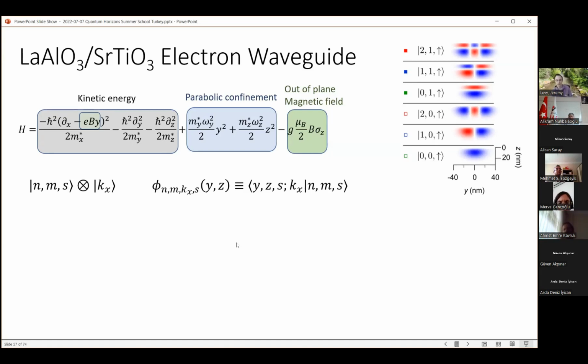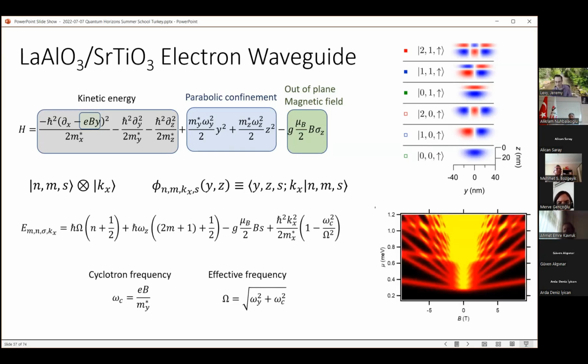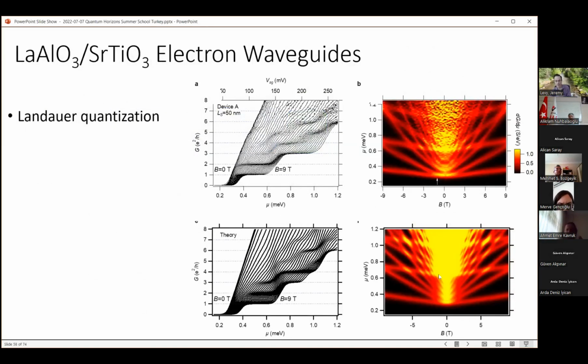And the energies themselves will shift in a magnetic field. And this is a plot of each of these red lines represents the bottoms of those subbands as a function of magnetic field along the horizontal axis and chemical potential along the vertical axis. So I'm showing you this because we can actually measure this experimentally. What you see here, again, the bottom is the theory and the top is the experiment. So if we measure for one of these devices, as we change the gate voltage, the chemical potential, we see these plateaus. If we differentiate these curves, you get an intensity plot. So this red line here represents the transition between 0 and 1, and so forth.